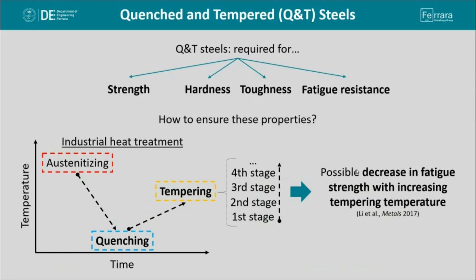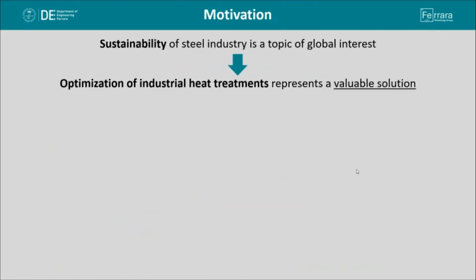Particularly, tempering includes different temperature ranges called stages, and each stage is associated to a specific resulting microstructure within the material. In this case, it is also important to state that, according to some literature studies, increasing tempering temperature seems to decrease the fatigue resistance of quenched and tempered steels. Nowadays, steel industry has to face important challenges regarding the optimization of heat treatments in order to get valuable achievements towards a more sustainable production.